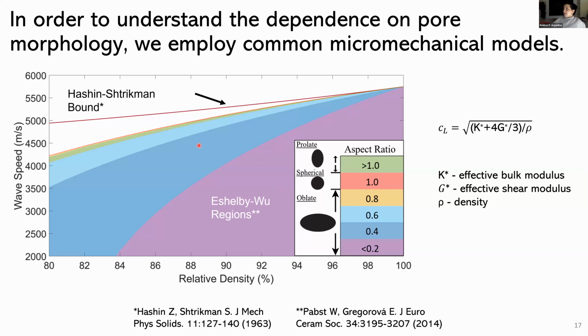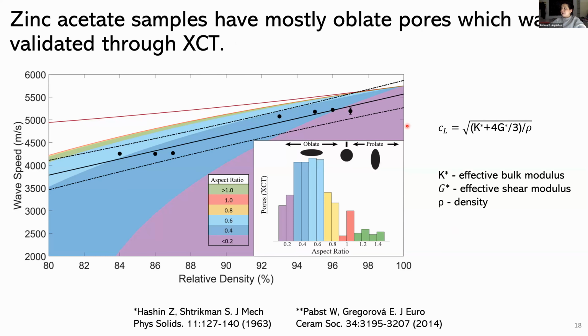So everything that you see in the purple and then in the light blue represents pores that are oblate. So that's oblate relative to the pressing direction. It makes sense that if you're doing a pressing process like we were doing in the sintering, that the pores would be oblate, or at least that's what we would have expected. And as you move to the green region, we're now getting prolate spherical and then prolate pores, so the ones that are elongated along that pressing direction. So now if I bring in the actual data that we collected for these, you see that they fall generally in that oblate region, so in that blue part that you see right here.